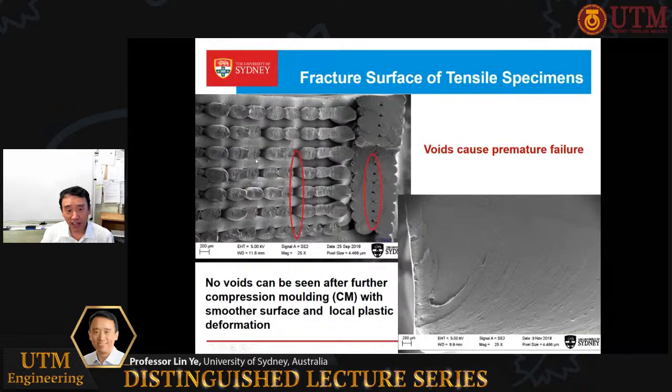Then the same material, if you put it into a mold, just like compression molding, will have a fracture surface like this. You can see there are no voids. Voids become a key player that causes premature failure for the 3D printed structure or component made by the FDM or FFF method.